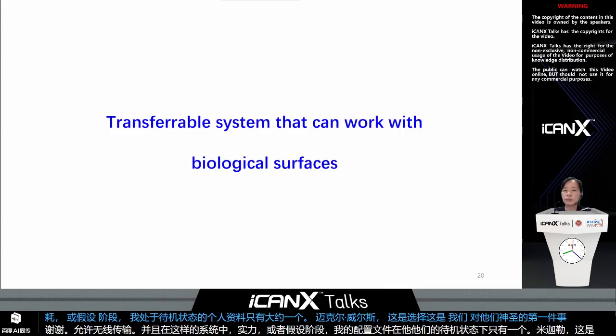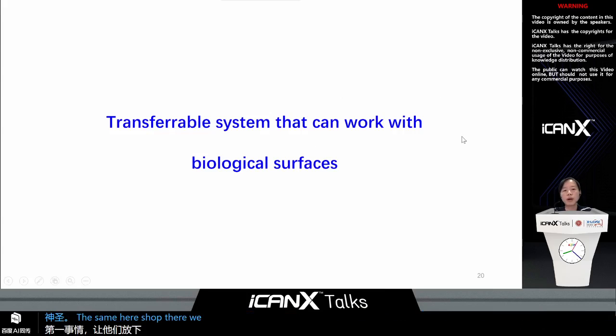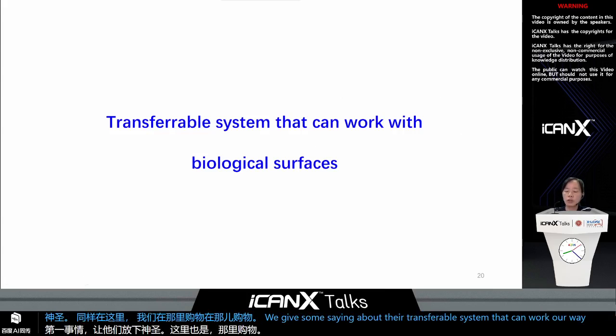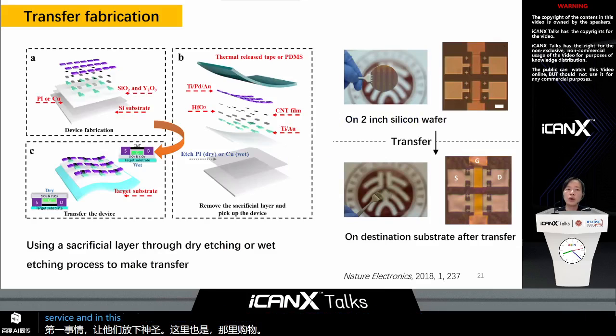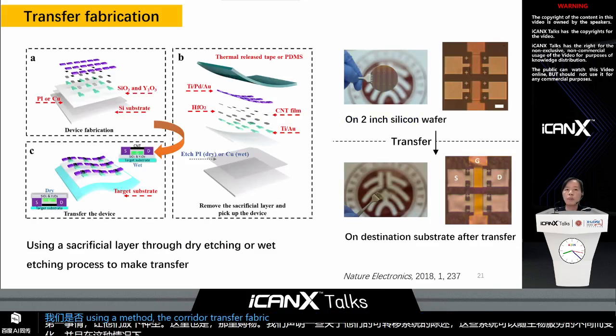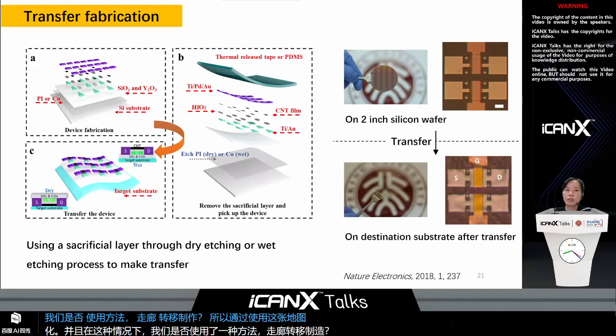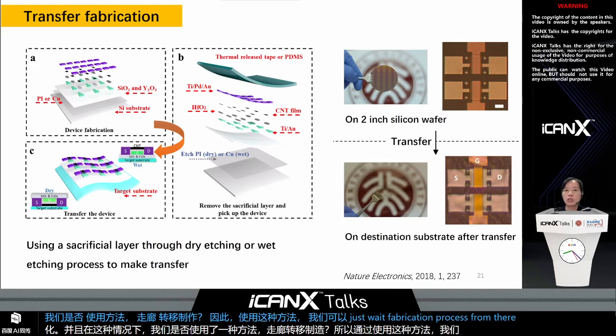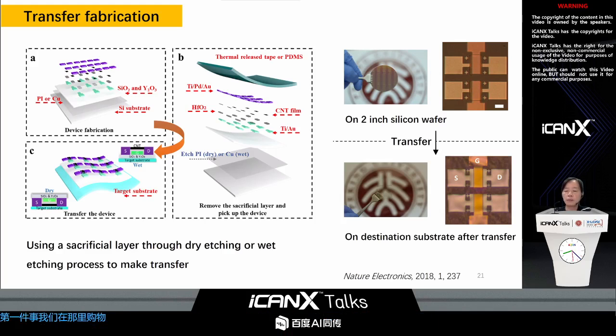The second thing we did is something about a transferable system that can work with biological surfaces. In this case, we use a method called transfer fabrication. By using this method, we can separate the fabrication process from the destination substrate, so we get rid of the limitations of fabrication on the polymer substrate. By introducing a sacrificial layer during fabrication, through dry etching or wet etching we can transfer the whole system at the end of fabrication to the destination or target substrate.